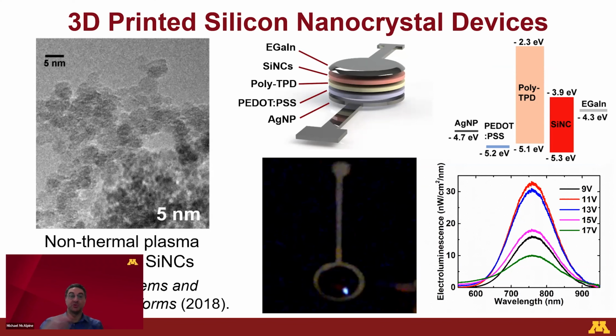So it does something which bulk silicon doesn't do, which is it emits light. So a wafer of silicon will not emit light. That's why you can't really put optics on your electrical chip, because silicon doesn't emit light in the bulk state, but these silicon particles do. So we can actually create an LED here based on these silicon particles. As you can see, it glows red. So that's red emission, band gap emission, essentially from these silicon quantum dots that were given to us, building up the same type of device that you saw before. Okay.